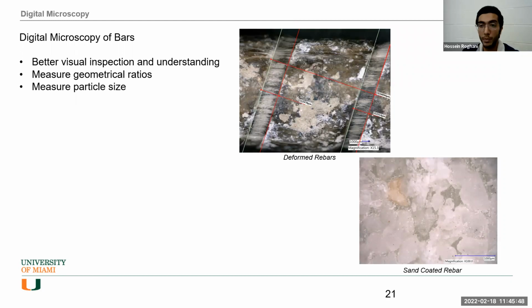In addition to the surface profilometers to come up with the surface roughness, there are other parameters that are important in surface profilometry besides the roughness. They are the geometrical ratios, like the rib height, the rib area, and all those things. These are for the deformed bars, I mean for the grooved ones and the helically wrapped ones. But in the sand-coated bars, which we call non-deformed rebars, the particle size is very important.